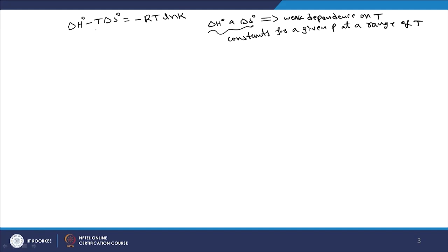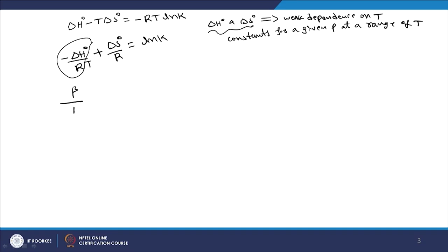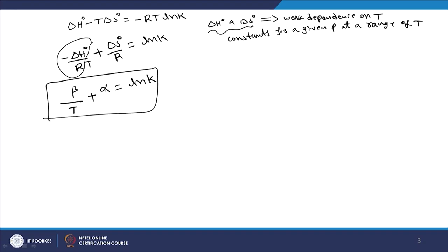By treating delta H° and delta S° as constants — meaning they do not change with temperature — we can write: minus delta H° / RT plus delta S° / R equals ln K. This quantity minus delta H° / R is a constant, which we call beta, and delta S° / R is alpha. So: beta/T plus alpha equals ln K. We need the values of beta and alpha to know the equilibrium constant for a particular reaction.